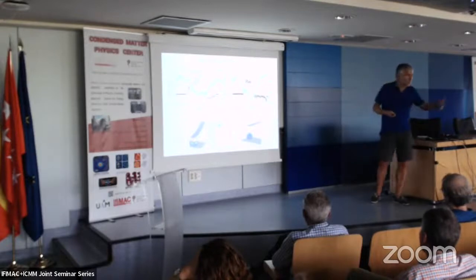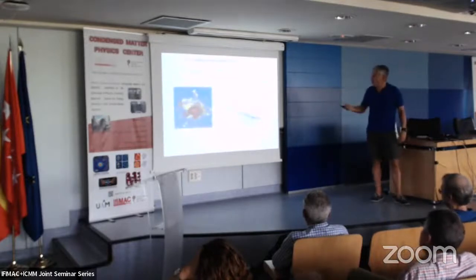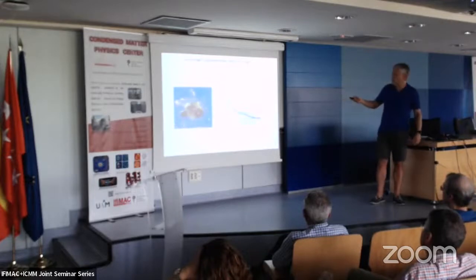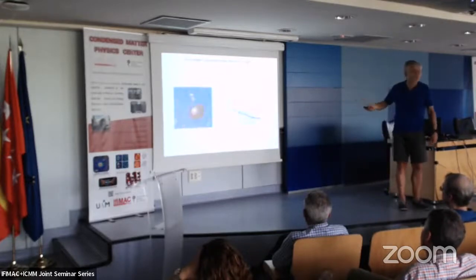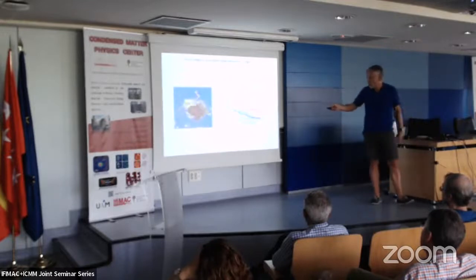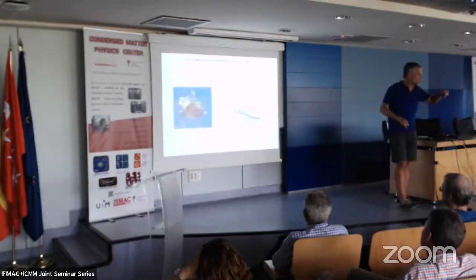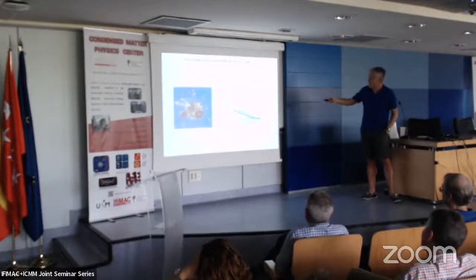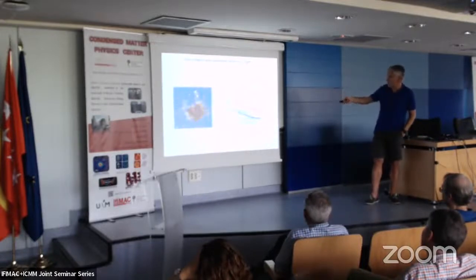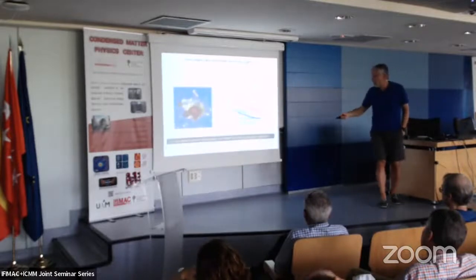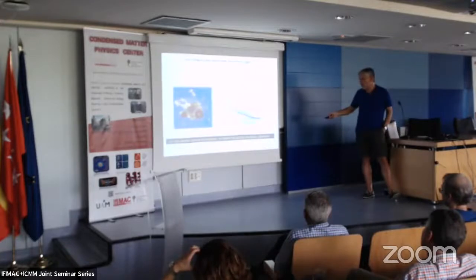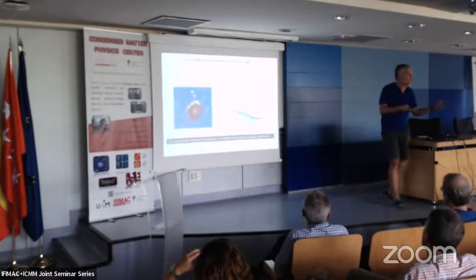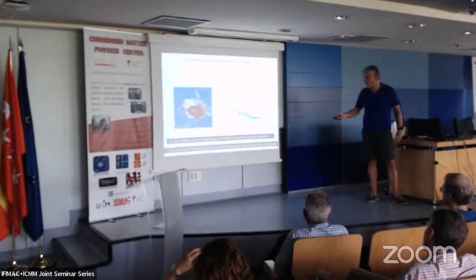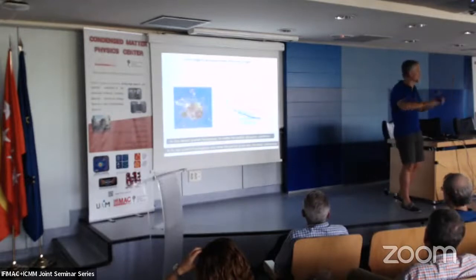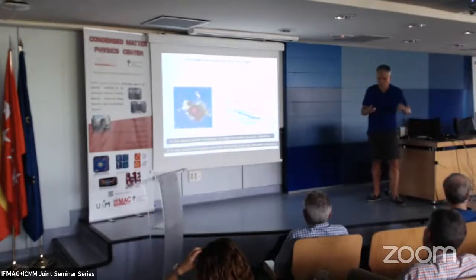So in order to go deeper into the difference, another experiment you can do is to check how the quenching changes. The quenching is the reduction of light as a function of the virus integrity. So here we are destroying the virus in a more or less controlled way, indenting the virus sequentially, okay? And here you see what happened with gold tips and with silicon nitride, you see there is a gap. So the conclusion here is that gold tips always quench the process, no matter the particle disruption, okay? So it means that we have kind of electronic quenching here. However, in the case of silicon nitride, the tip quenches the process only when the particle is not very disrupted. So it has to be more or less intact in order to have quenching. So this is telling you there are two mechanisms of quenching.